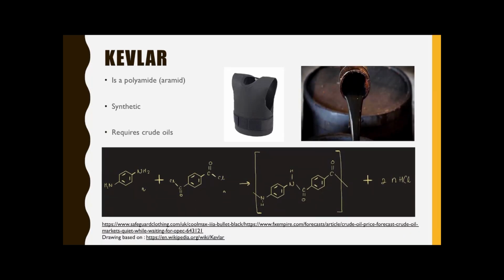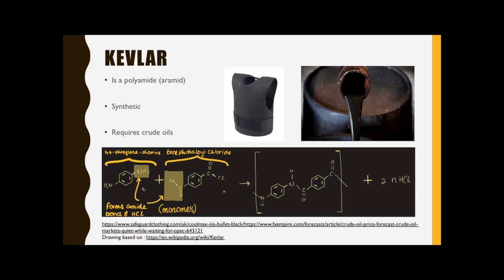Let's talk about Kevlar. It's a polyamide, more specifically an aramid. It's synthetic and requires crude oils to make. The monomers are 1,4-phenylene diamine and terephthaloyl chloride. They form an amide bond between them and one molecule of hydrochloric acid. Polymers are formed, which is the Kevlar, and as you can see, they are attached via the amide bond. The HCl needs to be removed.